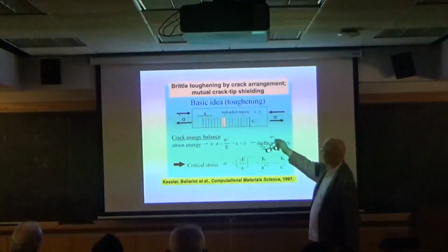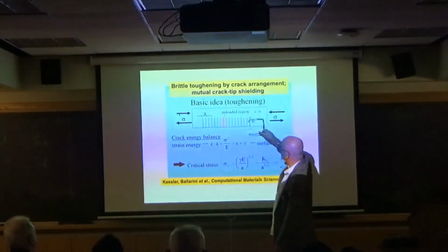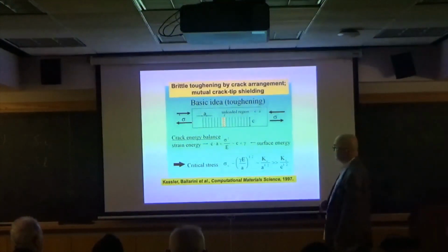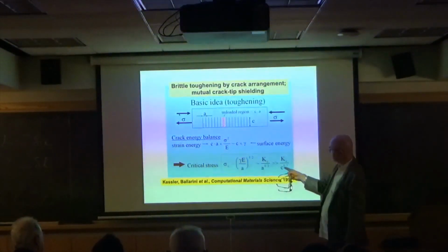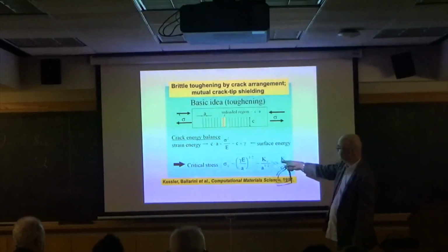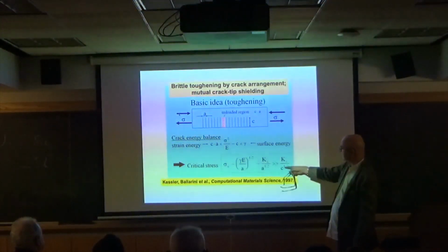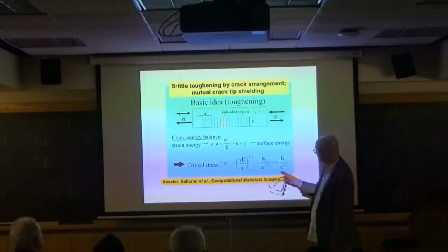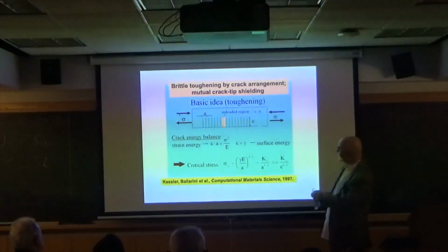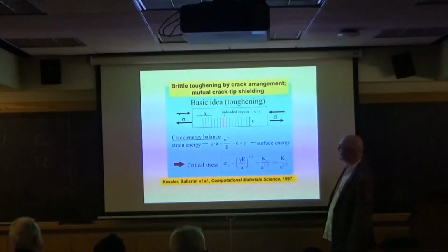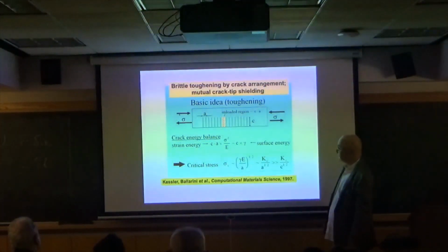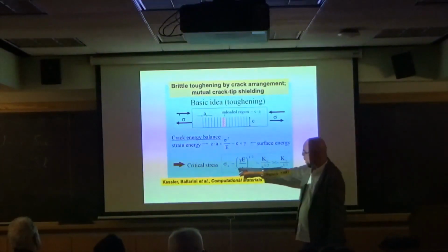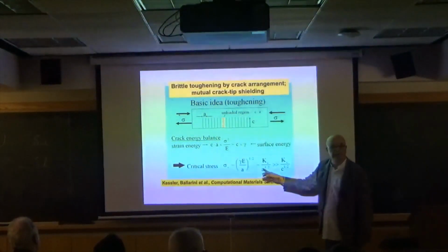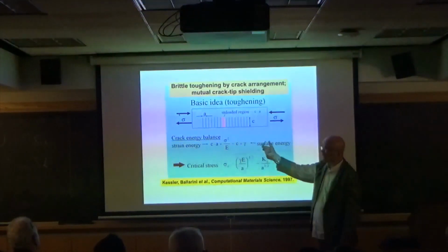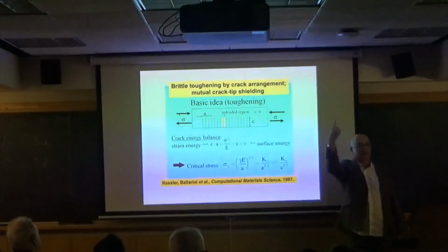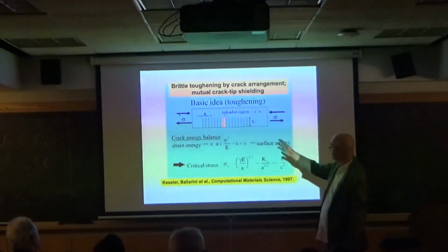So the idea is, if you have a crack that has spacing A and crack length C, if you have an isolated crack, then the strength is inversely proportional to the square root of the crack length. And this is the fracture toughness of the material. So if your cracks get longer, it's in the denominator, the strength gets less when the crack is by itself. But if you put cracks together, you could show now through very sophisticated stress analyses or energy arguments, which take a long time, that now the strength is inversely proportional to the square root of the spacing, which means when the spacing gets small, it's in the denominator, the strength goes up. So you get a material much stronger by having many, many cracks.